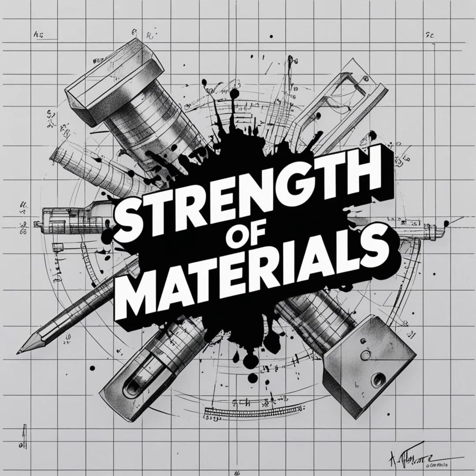The net result is a highly uniform, dense layer of material at the surface locked in a permanent, powerful state of residual compression. It is identical to the tempered glass. Typically, the residual compressive stress produced by shot peening is at least half the yield strength of the material being peened. Half the yield strength. That's a massive, invisible protective shield built right into the metal.